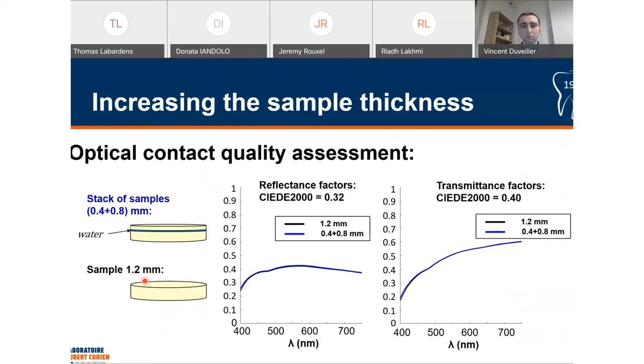As the thickness is the same, the measurements should also be the same. As you can see here and here, for the reflectance factor on the left and for the transmittance factor on the right, the curves overlap almost perfectly and the color distance between the two curves is very low. So we can consider that the optical contact performed with water is good enough. So now we can stack our samples together in different combinations, up to a maximum thickness of 3.4 millimeters when we stack our four samples together, and try our corrected Kubelka-Munk model on them.